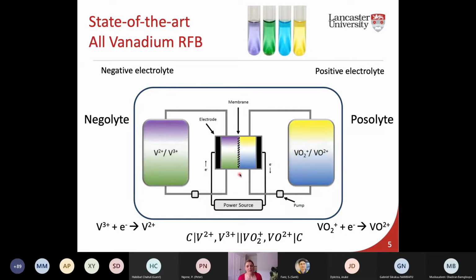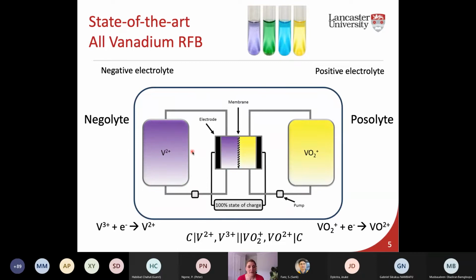And that gives you fewer constraints on this membrane, because what we want to avoid is metal crossover through this membrane back and forth, which would essentially self-discharge the battery. But if we get vanadium crossover through one side or the other, then it all sort of equalizes out. Yes, there's a slight disparity in the oxidation state, but it still works out for it to stabilize. So we don't get contamination in the battery as such. There are other issues, however.